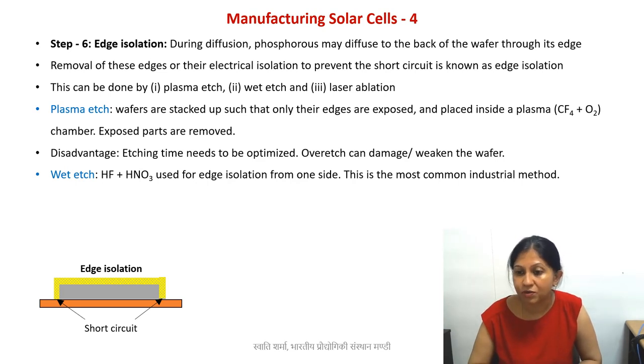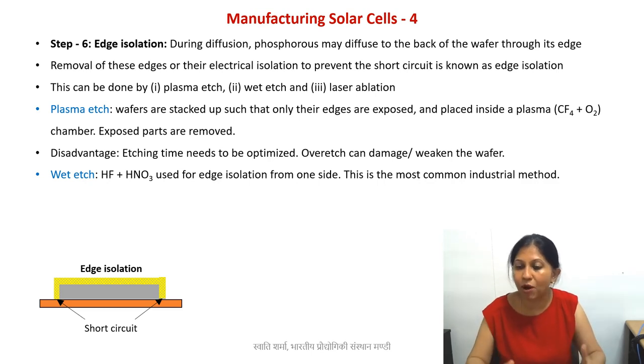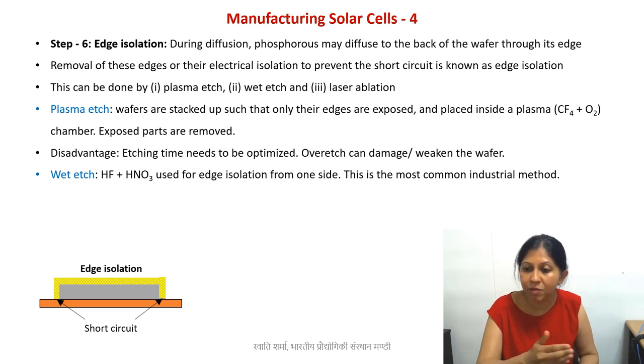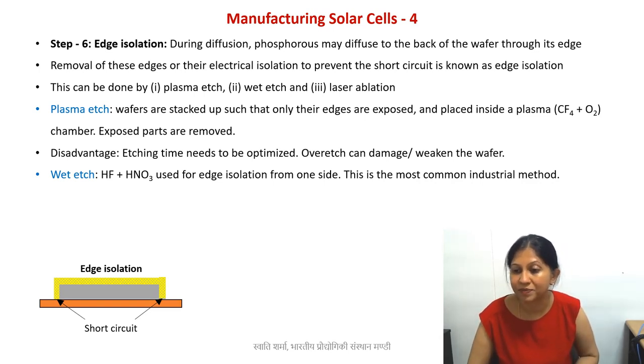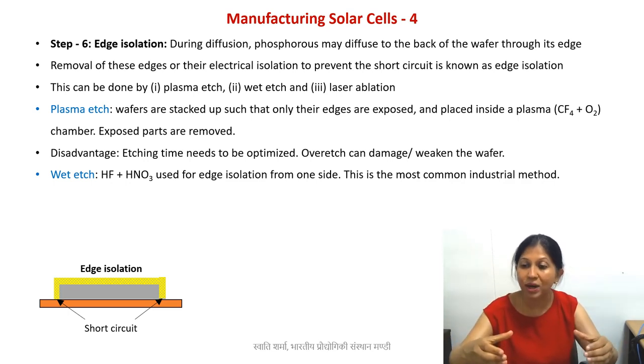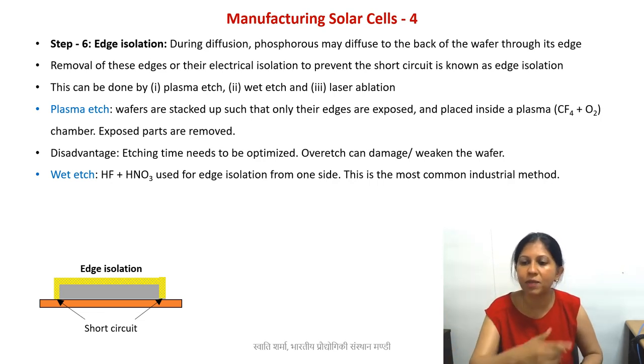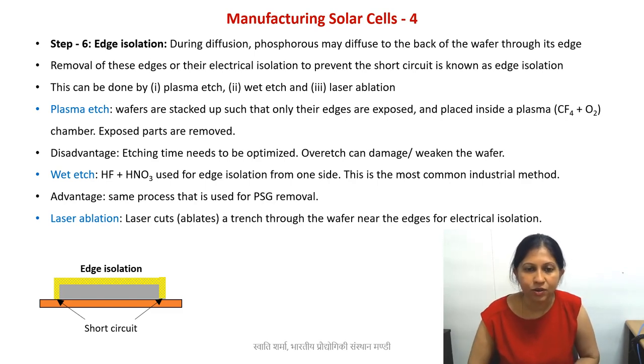The second process is wet etching, which means using chemicals. Here we use hydrogen fluoride and nitric acid. This combination is the most commonly used in industry. The reason is that we use the same pot and similar chemicals for removing the PSG — the phosphosilicate glass — which we learned in the previous lecture. So since you already have this PSG removal pot, you can also do this edge isolation step in the same pot. With square-shaped wafers, you dip one side, rotate, then dip the other side. It's an easy and common process, and the advantage is that you can use the same pot.